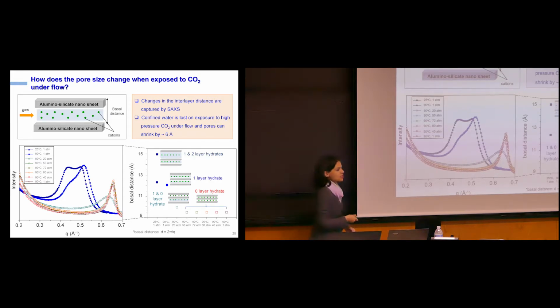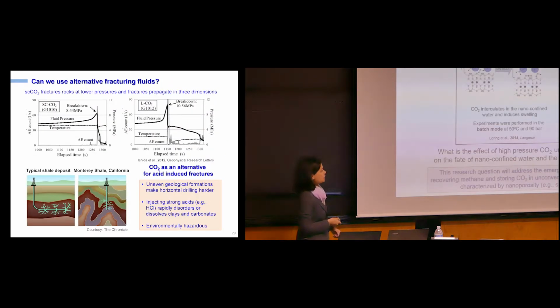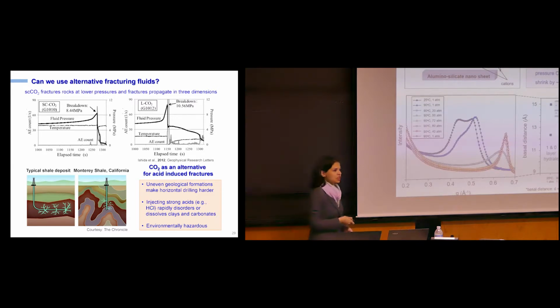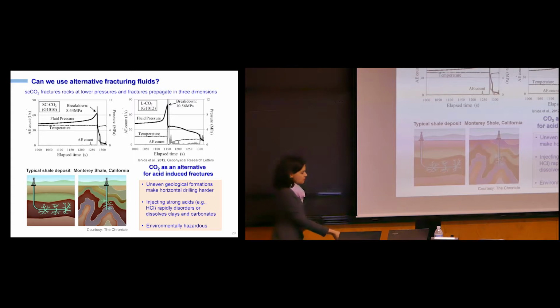And these are some of the first set of data, and this actually goes counter to some of the work that was reported at PNNL, where they actually showed that when you have CO2, it goes into some of these environments and causes the materials to swell. We actually see shrinkage as a result of CO2 interactions. So that was an important finding for us.